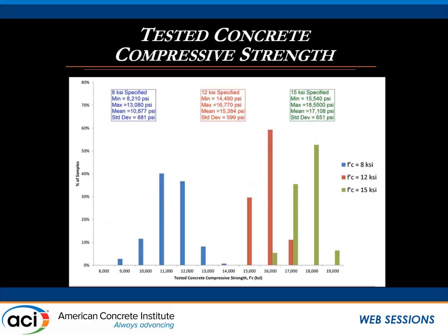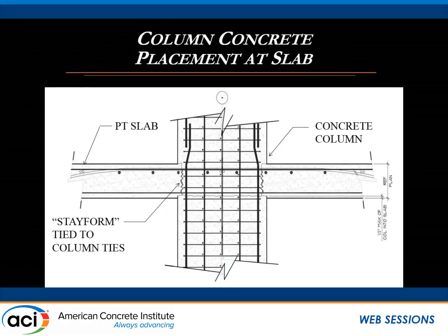This is a summary of the 8,000, 12,000, and 15,000 PSI mixes on the job. You can see here the average of the 15,000 was 17,108 PSI, and the maximum broke about 18,500. The standard deviation was 651. So we were getting way above the specified strengths that we called out on our drawings. Now, how do you deal with the issue of puddling?